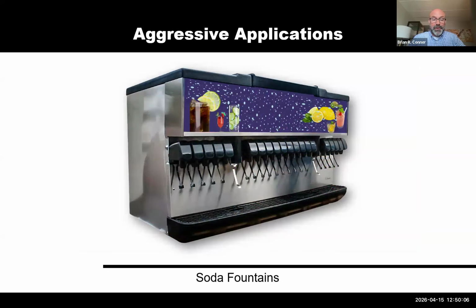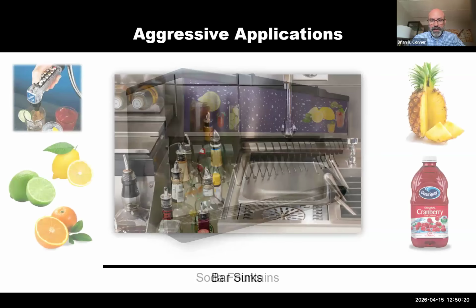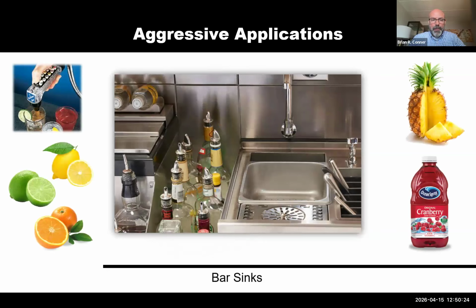These aggressive applications, you think about the soda fountains, which I mentioned just a second ago. The pH of soda is such that you can drop a 16 penny nail into a liter of soda, and within a week it is totally dissolved. So quite aggressive. Most of us don't think about it, but the pH levels of juices are down around 1, 2, and 3, depending on the juice, which is very acidic and causes a lot of damage to metallics, which is why in commercial kitchens, most of the material used on any surface area where they're prepping things is going to be stainless.